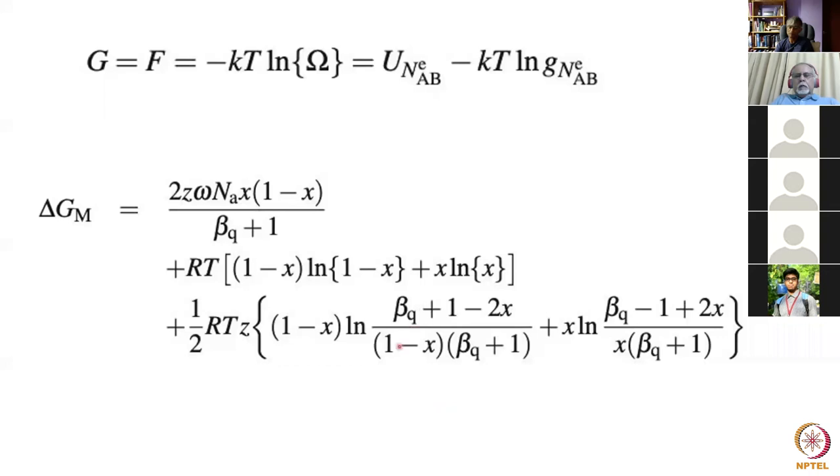These terms become important. If you go to my website and look for a paper on the diffusion of carbon in austenite, Siller and McLellan did a lot of work on this, and I derived some coefficients for that work. You will see that it beautifully represents the concentration dependence of the diffusion coefficient of carbon in austenite. So there are cases where we cannot simply use empirical terms.